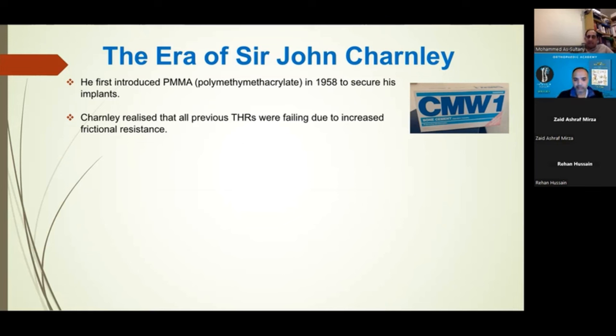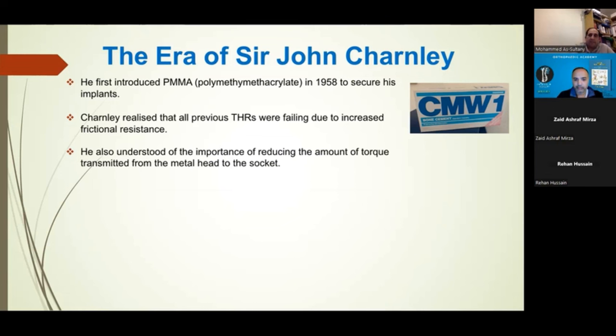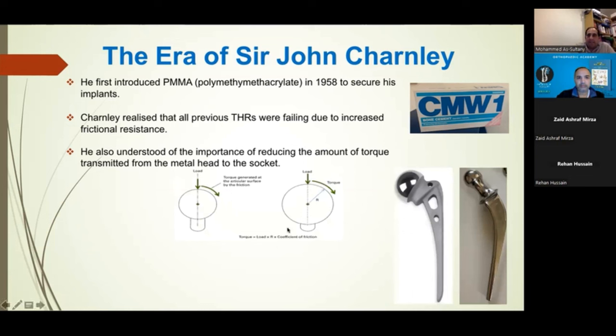So he then realized that it was important to try and reduce the amount of torque transmitted from the bearing surface onto the implant bone interface. Because if you had a lot of resistance, a lot of torque at the bearing surface, then that force would be transmitted to the implant bone interface. And that's where you would then get movement of the entire implant. So that interface will fail.